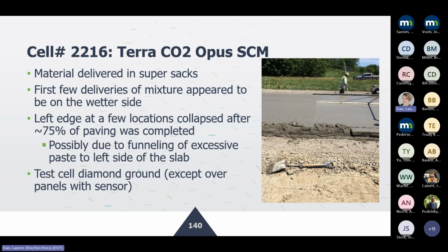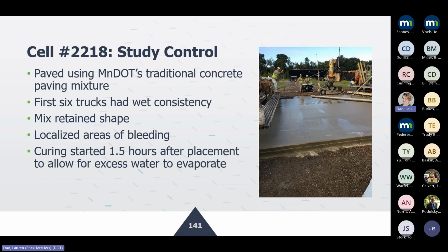And the next cell, 2016 TerraCO2, again super sacks, and not many issues with this mix, except once 75% of the paving was completed, we did see some of the edges that were falling apart. They did collapse, and then they had to be readjusted and finished after the fact. And then this test cell was also diamond ground completely, except all the cells with the sensors.